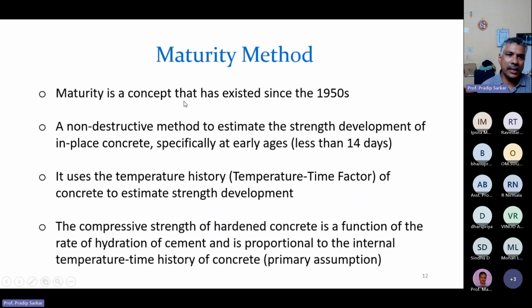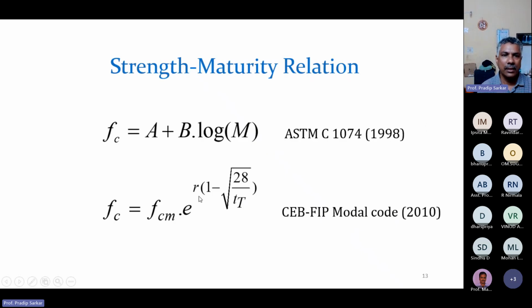Maturity is a concept that has existed since the 1950s, a non-destructive method to estimate the strength development of in-place concrete, especially at early ages, that is, less than 14 days. It uses the temperature history, the temperature-time factor of concrete, to estimate the strength development. The compressive strength of hardened concrete is a function of the rate of hydration of cement and is proportional to the internal temperature-time history of concrete. This is the primary assumption of the maturity method.